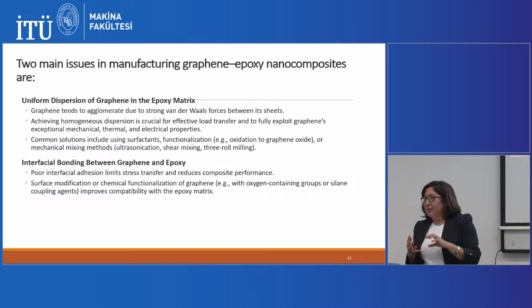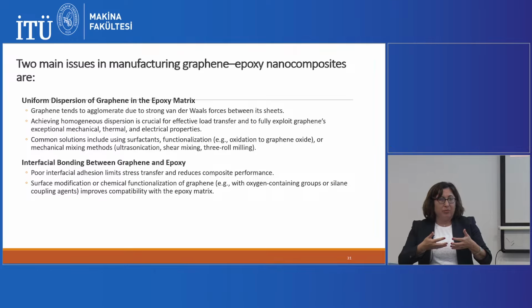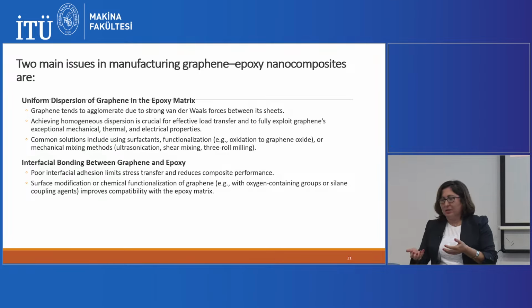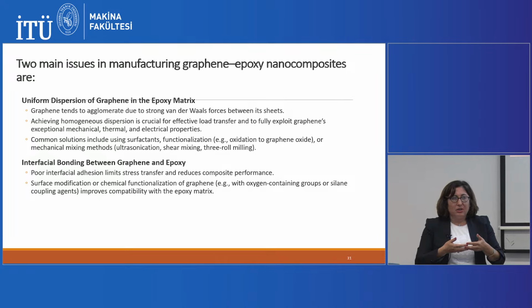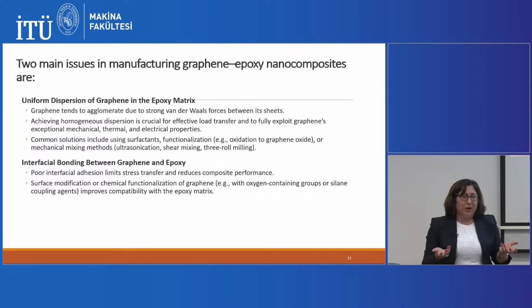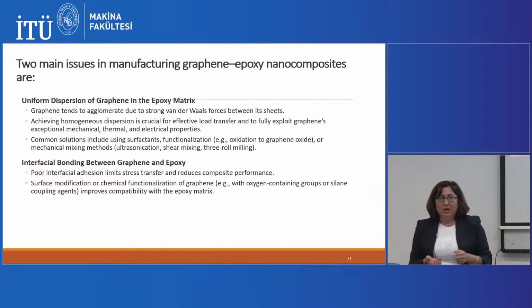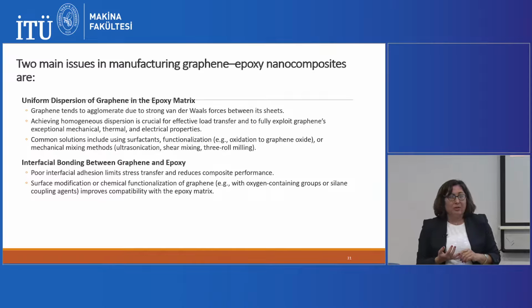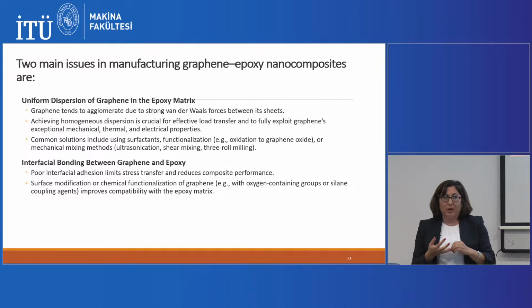One thing, when you use those nanoparticles in the polymers, of course, there is going to be an interface. There should be a connection from graphene to the matrix. If you cannot establish this connection very well, it doesn't matter how powerful the graphene is, you get nothing. So this is one thing. The one issue is this one. This interface needs to be developed.